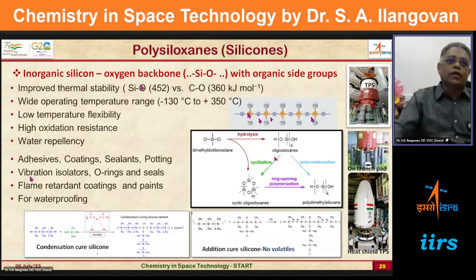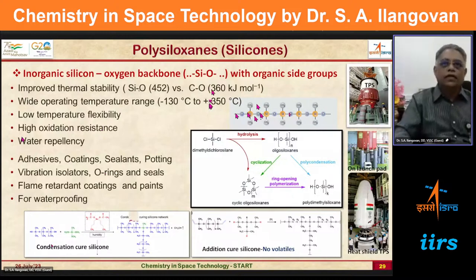Then, if I am able to make it in a flexible way, it will be a vibration isolator also. And O-rings are getting formed. Flame retardant coatings are coming out from this, and higher oxidation resistance materials. And since this has the SiO bond, hydrophilicity is less, where we use water repellent coatings also. So by changing over from CO and bringing the family of SiO, we are able to include various parameters. You can see the high temperature side. Earlier I was showing 100 for carbon. Now it is 350, right? It is because of the bond energy that we are able to increase the temperature capability from 100 degrees for other carbon based materials to 350 for silicon material.